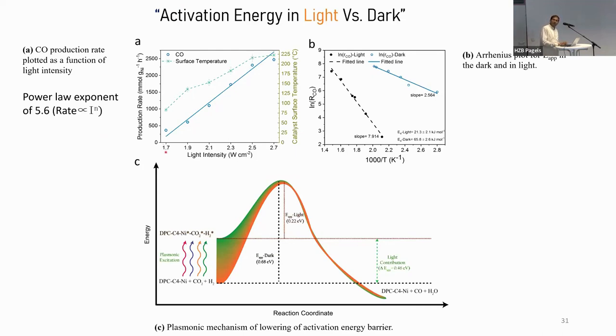See 1.7, 1.8, 2.1. So we kept changing the light intensity onto the black gold. And you see there's a super linear relationship between the light intensity and the production rate, which again indicates that it is the hot electron mediated reaction and not a thermal reaction. We also carried out the activation energy barriers in light and dark, and you can see in light it's around 0.22 eV versus in dark it's 0.68 eV, again indicating the role of light in reducing the activation energy barrier.